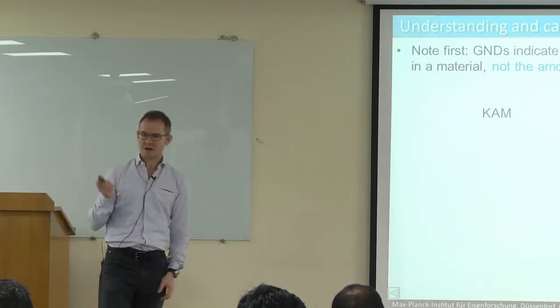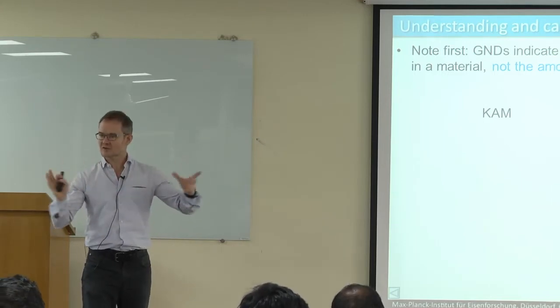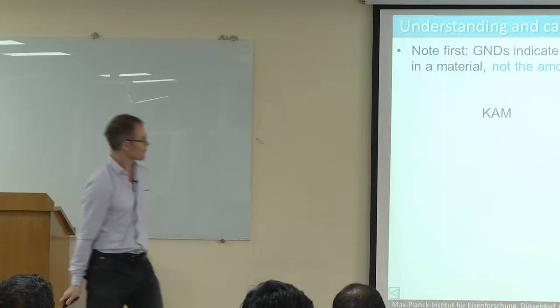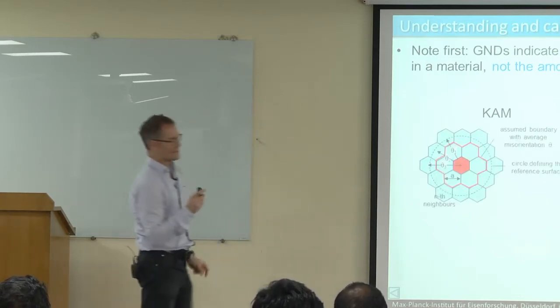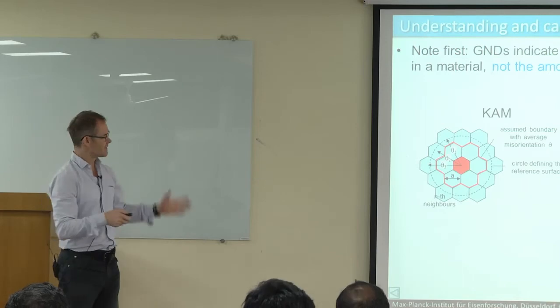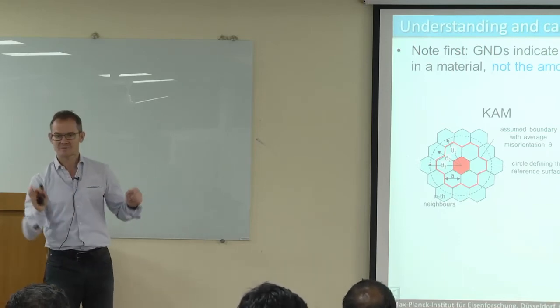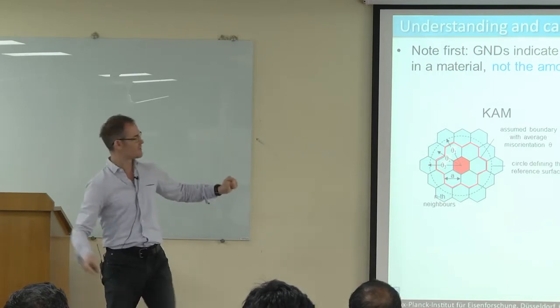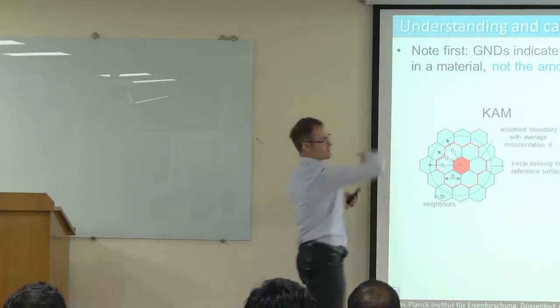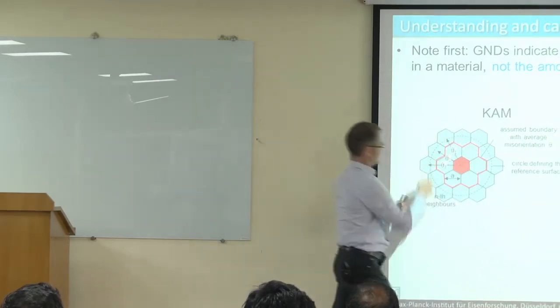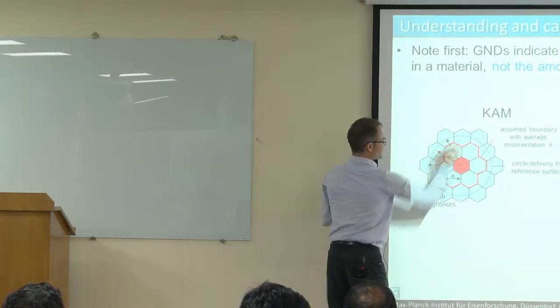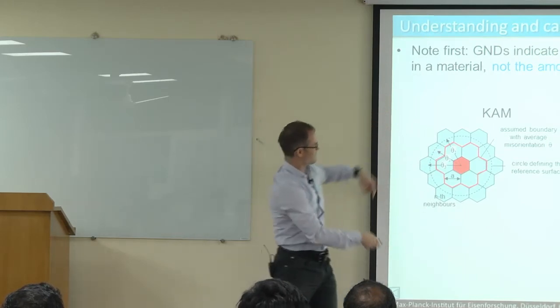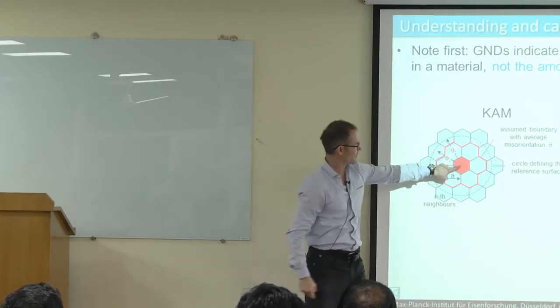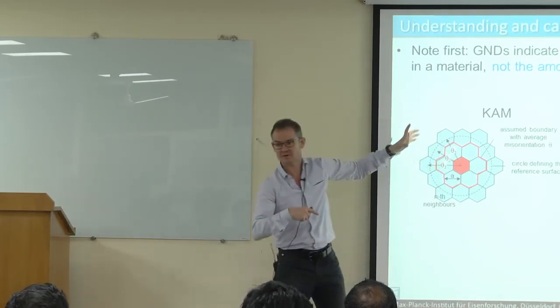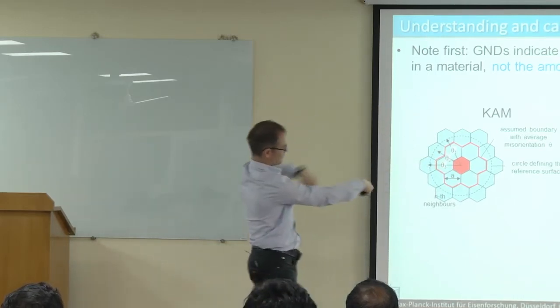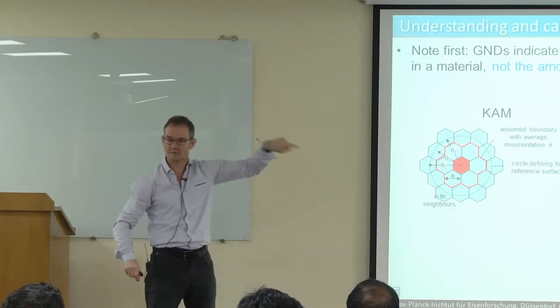So now how can we measure them? How can we measure these GNDs, even knowing that this is a limited concept? But it's nevertheless an interesting concept. We use in EBSD something which is called kernel average misorientation. Also, again, later on we'll talk more about that, but what does it mean? Imagine we have measured a very big map of EBSD, and this map consists of individual pixels. I see all the pixels in a very large map, but I take out only a kernel here. A kernel is one center point with all its neighbors around. This could go on forever here, this plot of little hexagons. Each one is just one measurement.